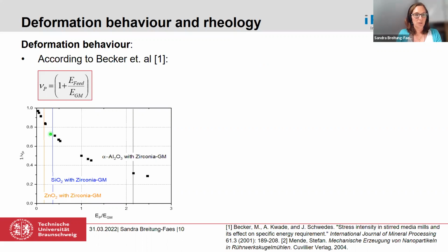And especially for the fused corundum, you have reduction values of around 70%. So only 30% of the energy, which is at least provided by the grinding beads or could be provided by the grinding beads, is really transferred to the material due to the different deformation behavior. So here it would be a good hint to say, okay, the grinding bead material should be adapted to the material as much as possible. So if you have really hard material, it is helpful to also use very stiff grinding bead material.